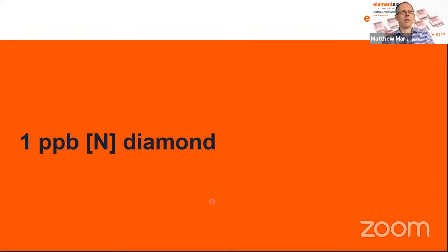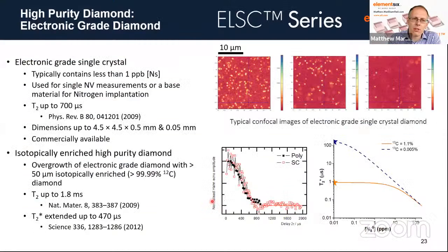So moving on to a very different regime, and this is the regime where Mathieu, after me, will be talking about sensing using single defects. And so this is where you need a much higher purity material, so a much lower concentration of nitrogen. And this is a product that's been around a while now, but I'll just briefly talk about it, which is our electronic grade diamond, which basically consists of less than 1 part per billion of nitrogen,